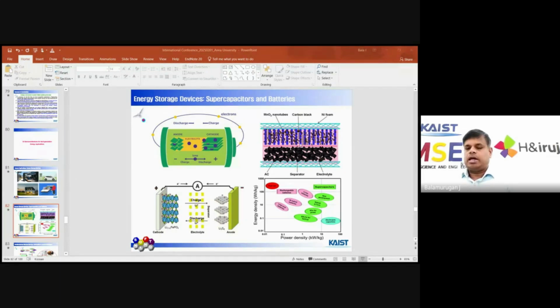In commercial capacitors, we use activated carbon as the negative electrode, and for the positive electrode we use metal oxides. But in a battery, usually for the anode, people use graphite based or lithium based material, and for the cathode we usually use iron, cobalt, or some transition metal, with intercalation of lithium. During charge and discharge, the lithium is intercalated and de-intercalated through the electrolyte. Here you can see the cathode of the lithium ion battery, and this is the anode.